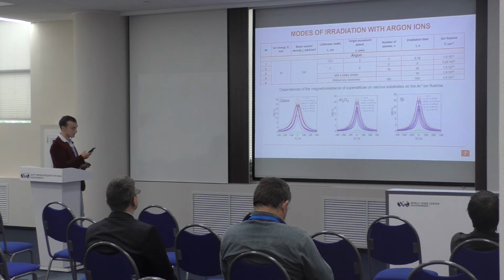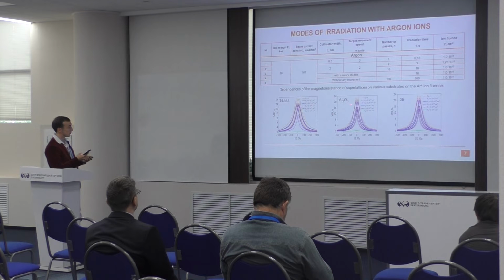When the fluence increases to the order of 10 to the power of 15 and 10 to the power of 16, the magnetoresistance continues to decrease. The graphs show that the magnetic saturation field also decreases as the fluence increases, and the transition to magnetic saturation becomes more abrupt.